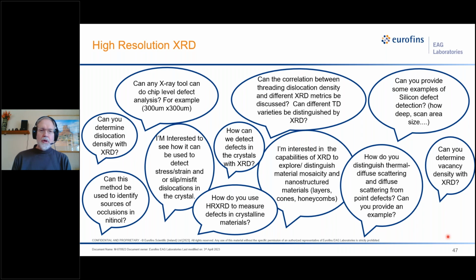That's going to reduce your peak widths from, say, on the order of a couple of tenths of a degree 2 theta to maybe 10 arc seconds, so 0.003 degrees, much narrower peaks. Once you do that, you can do a rocking curve like Stephanie talked about earlier. You sit on a particular diffraction peak and you scan the diffractometer in omega and measure how wide the peak is.